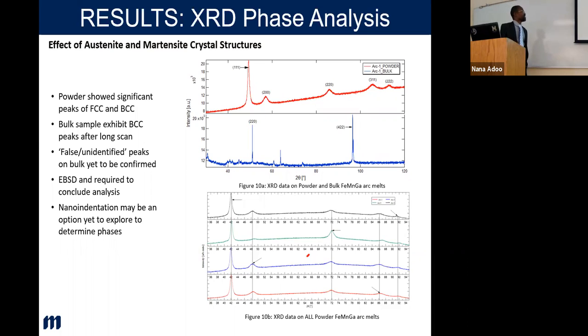So going back, I took the textured material and XRD'd it, and got these BCC peaks, which are conflicting as well. So these two cannot be the same, because we're talking of one material. And this is where, at this stage, it tells me that there is something that isn't right here. Even though I'm getting my results, I need to clean it up.